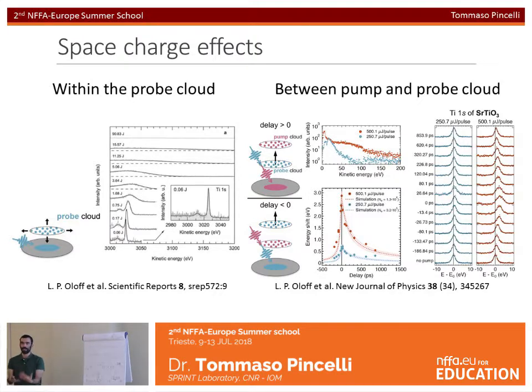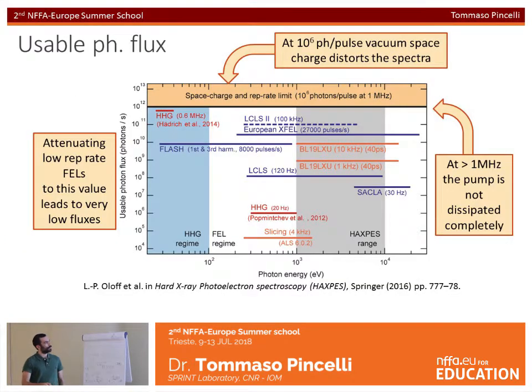So this is difficult to deal with. The simplest strategy to perform photoelectron spectroscopy is to go to high repetition rates and lower the power density of both the pump and the probe pulse. And here I show this image in which I have normalized to the maximum amount of photons that you can use before producing space charge in your spectra, which is 10 to the 6 photons per pulse. So if we reduce the amount of photons per pulse that you can use in a free electron laser that has a very low repetition rate, then you get usable photon fluxes that are very low. So you are dealing with bad statistics in your measurement.